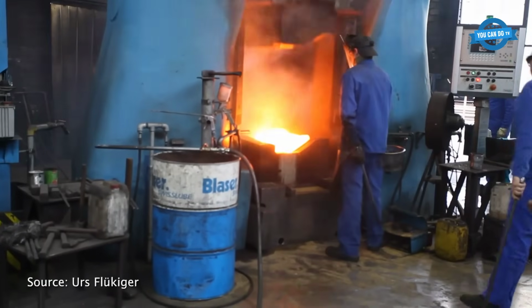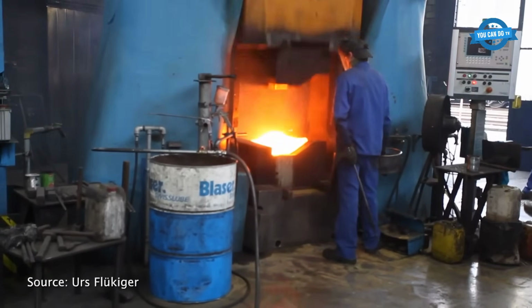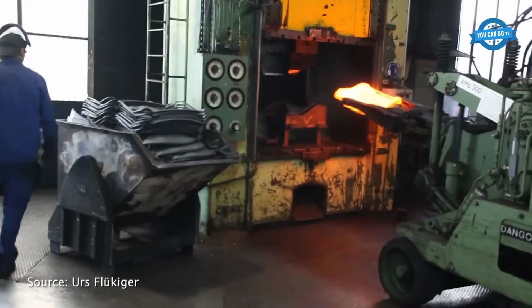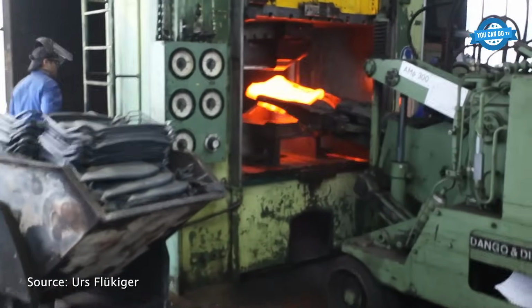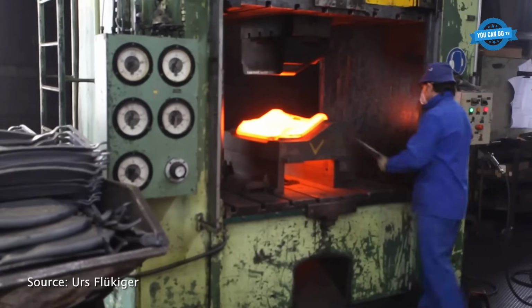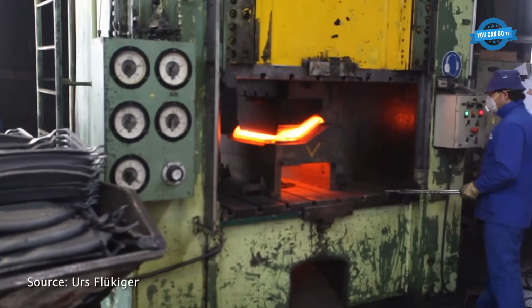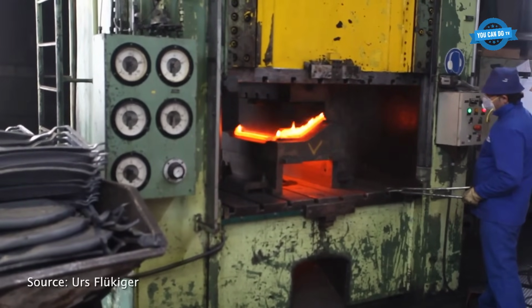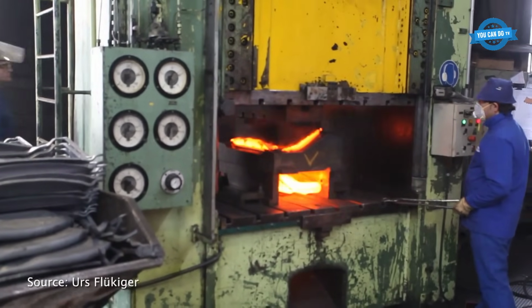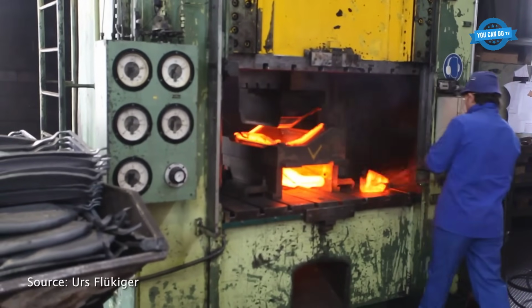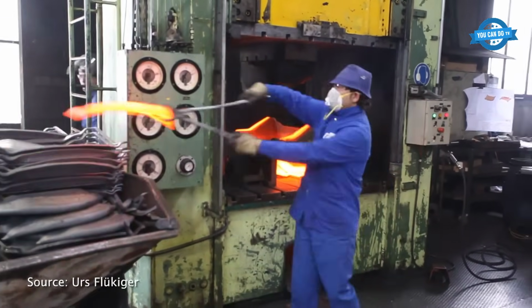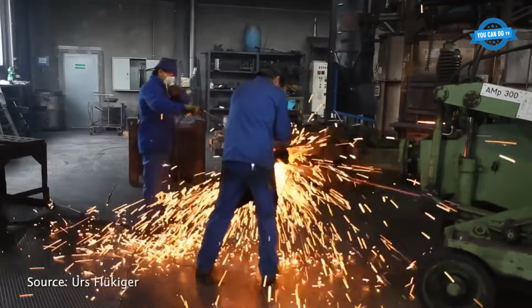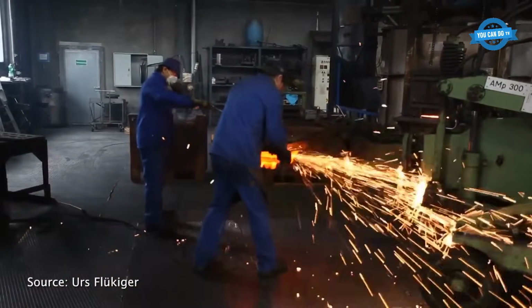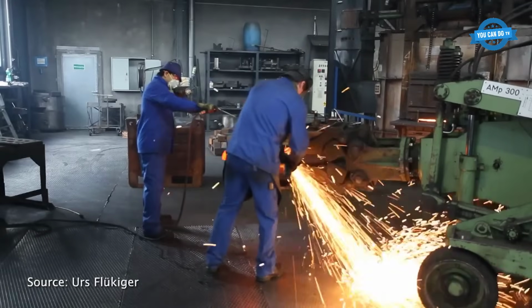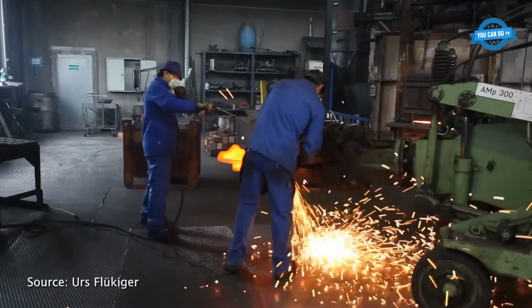The process requires 3 heating cycles, initially to 1,200 degrees Celsius, followed by 2 reheats in a gas-fired forge furnace, demanding over 100 strikes for final forging. After each forging stage, a 1982 400-ton press trims excess material. A manipulator handles the 300 kilogram part, while 3 skilled workers collaborate seamlessly, making it a fascinating display of teamwork and expertise.